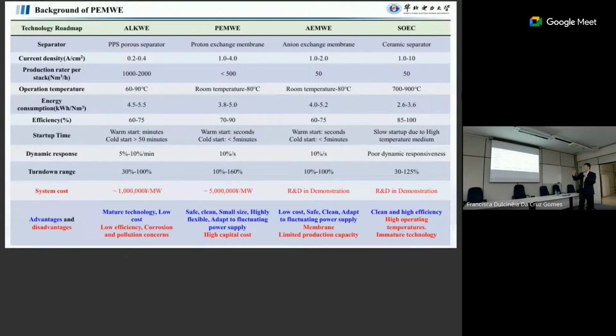Okay, but the main problem for PEM is that it is too expensive. The reason is that for the anode side, firstly, we have an acid environment. Sometimes we can reach pH equal to 2, a highly acidic environment. Then we have oxygen produced, so it's a highly oxidizing environment. Before, for fuel cells, we could use carbon materials. But in this environment, carbon material will be oxidized to CO2 immediately. So here we have to use titanium. But if we use titanium, the price is very high, and even titanium cannot resist for long. Then we need to put on valuable coatings, for example platinum. This makes the whole system more complicated. So most of the people working on PEM try to reduce the cost.